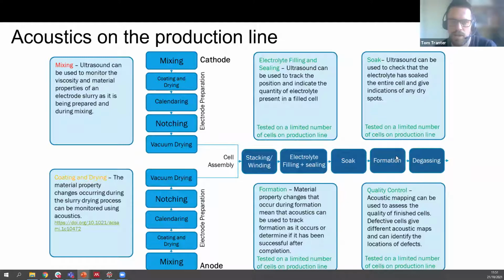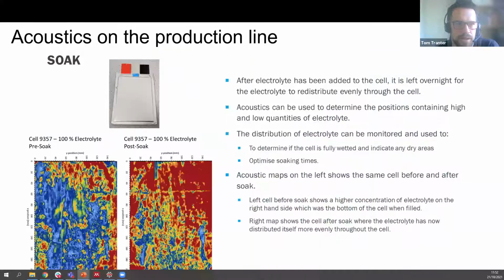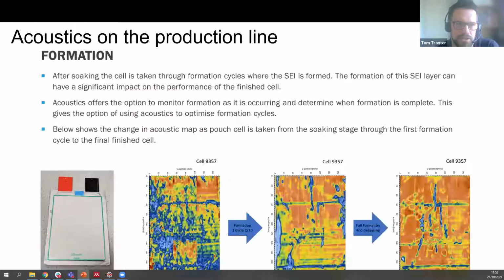So formation is actually a really long process. They have to cycle the cell very slowly for a number of days and then leave it to settle, if you like, and that takes a lot of time and energy. This is the traditional point to implement proper QA, but if we can implement it earlier on, we'll save time by eliminating those bad cells. And yeah, we can detect changes in the acoustic response at various stages.